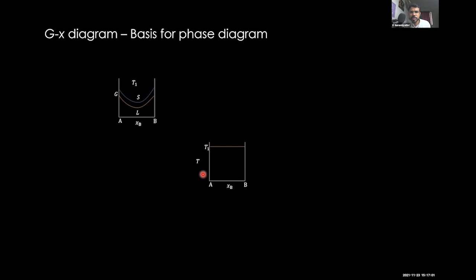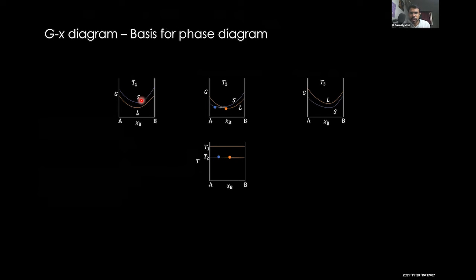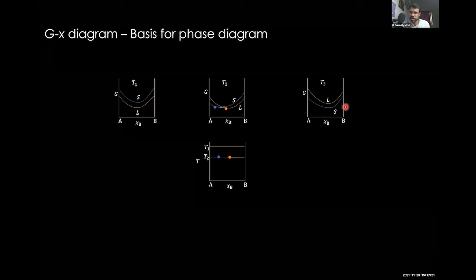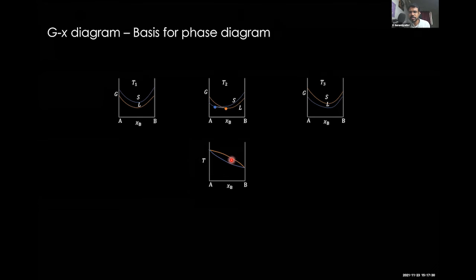So this gives you details of where the solid is stable, where the liquid is stable. T1, T2, T3 are three different temperatures. You will see that liquid is the lowest in some cases, solid is the lowest in some cases. Whichever has the lowest Gibbs energy will be the stable phase. Therefore, you can mark it in the phase diagram and get the entire phase diagram depending on different temperatures. So this is how a phase diagram comes from Gibbs energy.